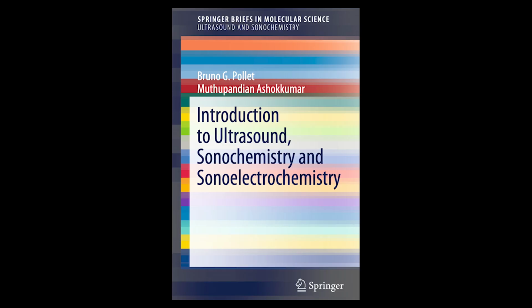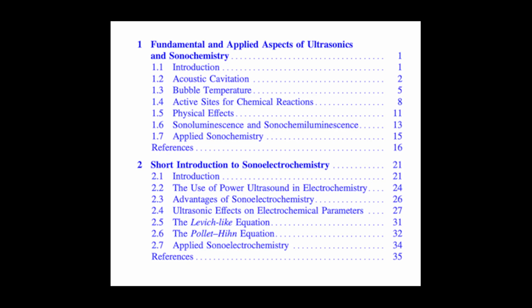And why is that important? Because this microstreaming acts as a very efficient form of localized mixing. It dramatically enhances mass transfer rates near the bubble and throughout the bulk solution, much more effectively than just stirring the whole beaker. This better mixing can significantly speed up reactions that might otherwise be limited by how fast reactants can get together. Okay, so physical effects: shockwaves for emulsification and erosion, microjets for intense cleaning and pitting, and microstreaming for enhanced mixing and mass transfer.